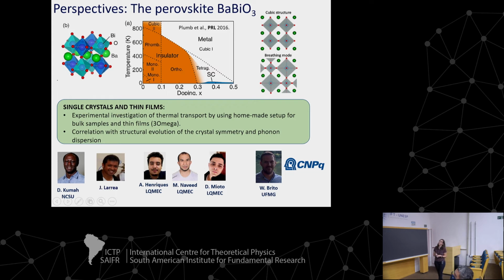Currently, we have selected another perovskite, BaBiO3, that also shows an emerging collective phenomenon like superconductivity, and this material was studied quite a lot in terms of p-doping. Superconductivity has a quite complex phase diagram. It's not cubic at room temperature, it's cubic only at very high temperature, and at room temperature it shows different distortions, a tilting distortion and a breathing distortion. So definitely at room temperature, it offers a quite interesting playground to try to connect phonon behavior and the structure. That is what we are interested in.